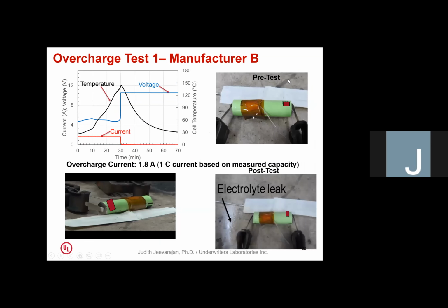And if we go into manufacturer B, which is the manufacturer that has the same label as manufacturer A but was bought online, we first did an overcharge test with 1.8 amp current, because we measured only 1.8 amp hours from it. So using that 1C rate, we did this overcharge test. And we see some smoke, but we see a lot of electrolyte leakage in this case.